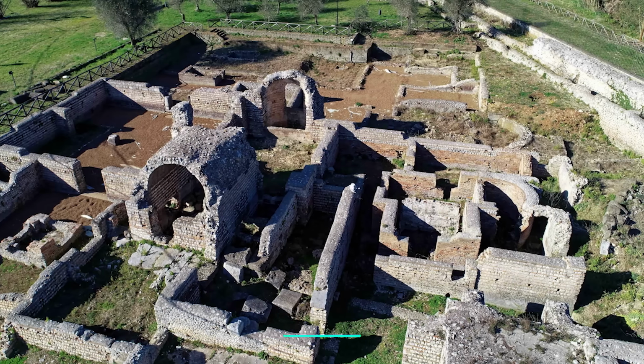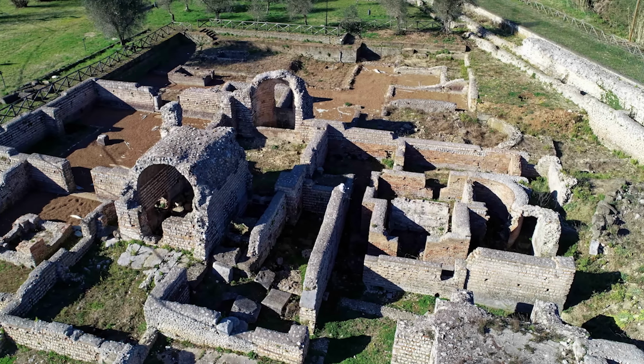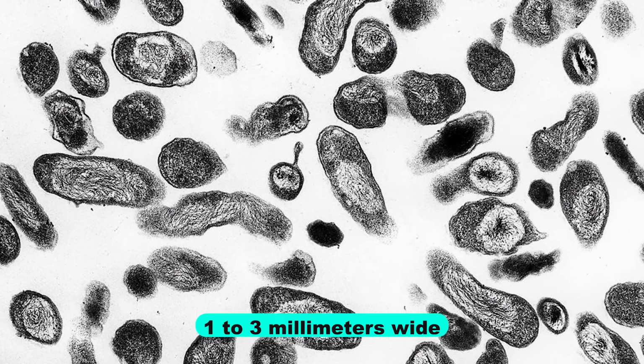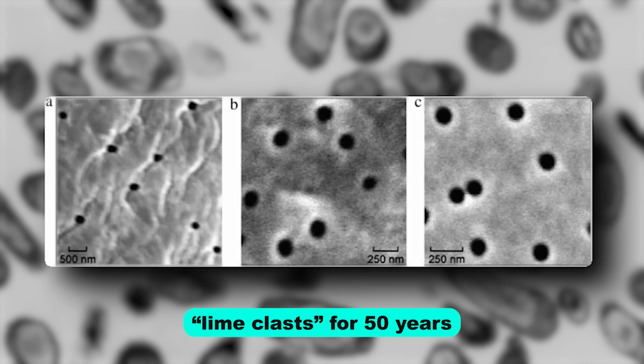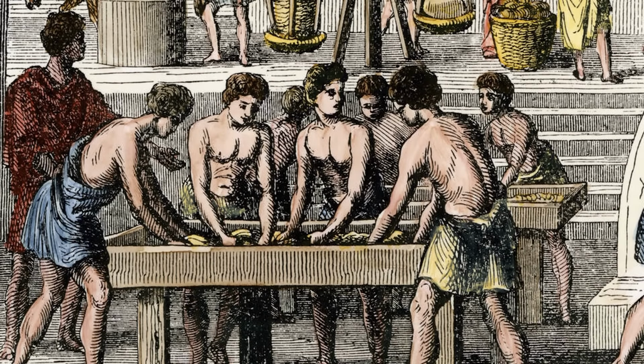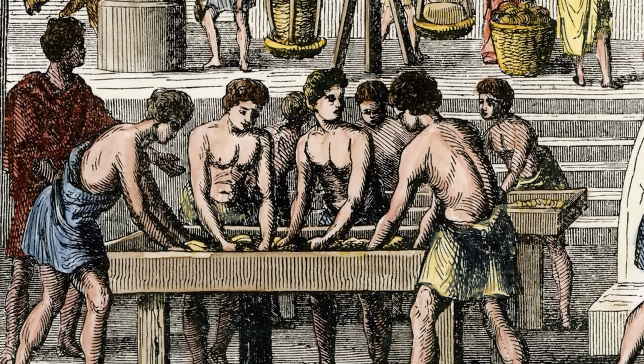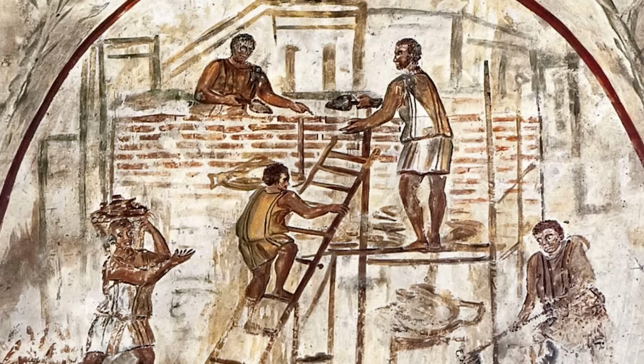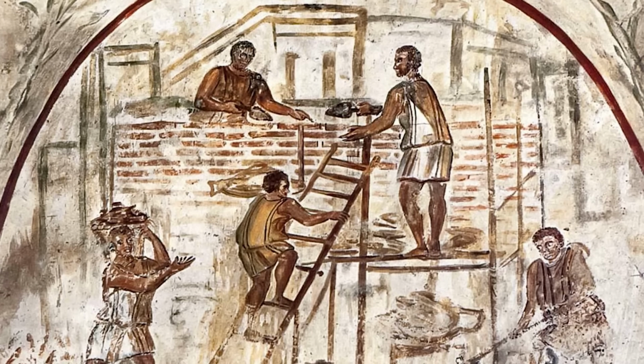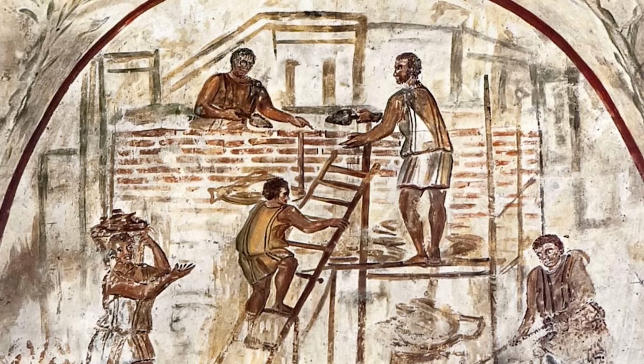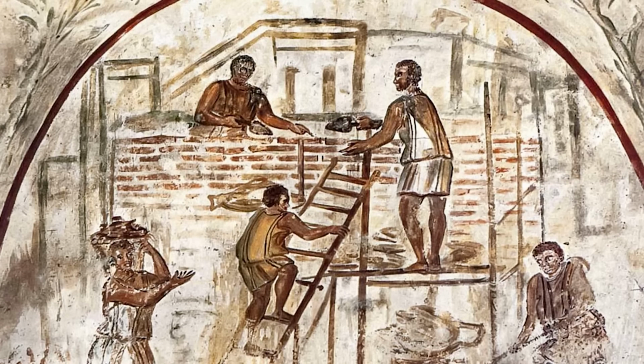The walls were poured around 30 BC, still standing. Under the electron microscope, the samples kept showing small white chunks, 1 to 3 millimetres wide, embedded in the concrete matrix. Modern chemists had been calling these lime clasts for 50 years and assumed they were defects. Sloppy mixing by Roman workers. A flaw in the recipe. Masic ran X-ray diffraction. He tested fresh concrete mixed 3 different ways. The lime clasts were not flaws. They were the entire point.